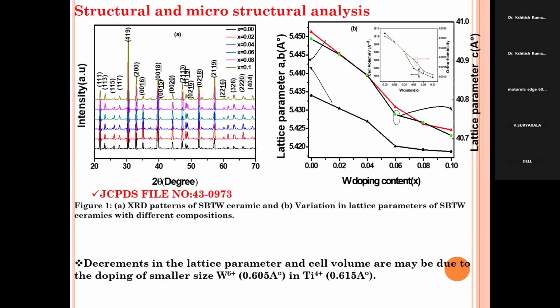So we confirm that the pure SBT is formed. And not only have we prepared the pure SBT, we have also doped tungsten on the titanium side. On the titanium side, we have taken different compositions, for example 0.02.